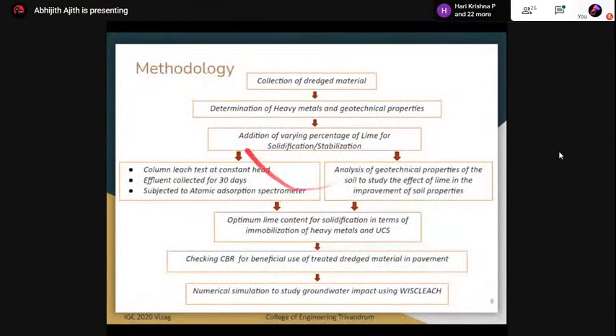I'll skip through this and come to the methodology. Initially the dredged material is collected and subjected to various geotechnical testing, and the heavy metals are determined using an X-ray fluorescence spectrometer. Then lime is added at varying contents, and a set of 6 treated samples is obtained. On both the treated and untreated samples, several column leach tests were conducted. Then the effluents were collected continuously for 30 days and subjected to an atomic absorption spectrometer to determine the concentration of these metals in the leachate.